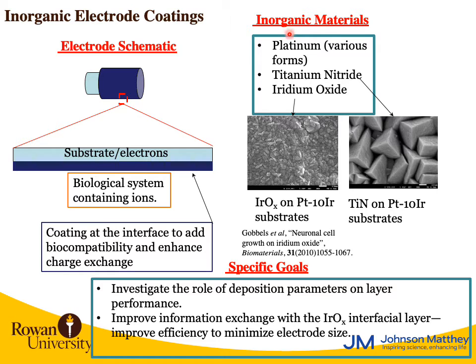The inorganic materials that are typically applied to these electrodes to help enhance biocompatibility and charge exchange are titanium nitride and iridium oxide. So we're going to be focused on the iridium oxide coatings here, and the specific goal of our work is to look at the role of deposition parameter on the layer performance. So we want to improve the information exchange between the ionic solution and the underlying substrate with this iridium oxide coating, and we're looking at the role of deposition parameter in how it influences that performance.